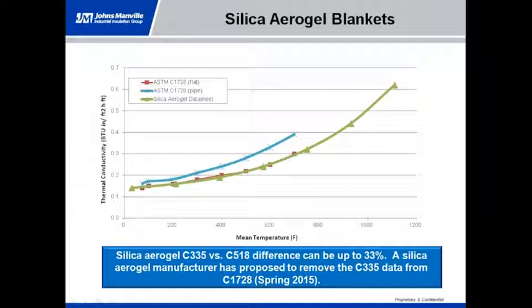Now, there has been a proposal to switch to removing the pipe section altogether, which, of course, people have the right to do. But the concern is, number one, if you don't have that information there, how are you going to know which application this is for unless it's explicitly stated in the standard? The other thing is, if you look at the silica aerogel line and the ASTM line, they overlap. On the previous slide, you can see that the products that were tested were significantly below that ASTM line. So there's enough room for production variation or installation defects, things like that, that you could get by using something that had been compromised or was a little bit off.